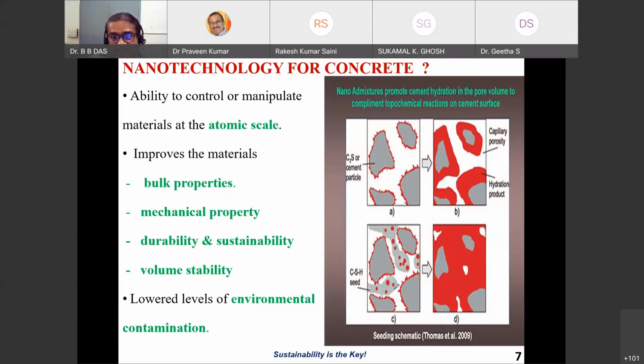Now you can see here there are some additional cement grains, where the nanoparticles, means individual nanoparticles. You must have seen the dots. These dots are nothing but your nanoparticles. Nanoparticles means you have introduced a very fine size particle into the cementitious matrix. Now, what is happening actually? What are these small circular dots? They are nothing but the calcium silicate hydrate seeds, which in the beginning itself, the nanoparticles started working as calcium silicate hydrate seeds. That is what is happening to the nanoparticles.